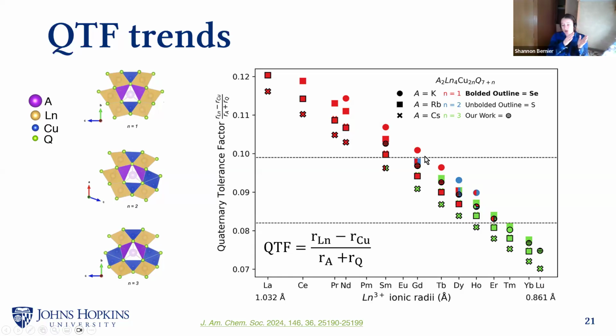Then as you lower the lanthanide radius, you reach a region of mixed phase stability where the materials can crystallize in any of the 3, moving until finally you reach the very small lanthanides. They will crystallize preferentially in the n=3 space group. And I should mention, these are all room temperature data points that if you'd like to take a deeper look at, you can see here in this paper. Greg's group really did synthesize all of these and measure their X-ray diffraction patterns in order to determine their exact space groups.